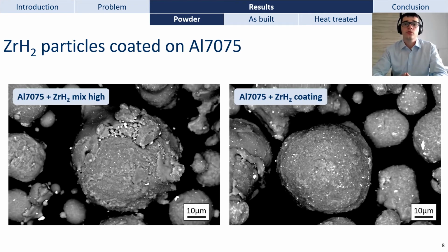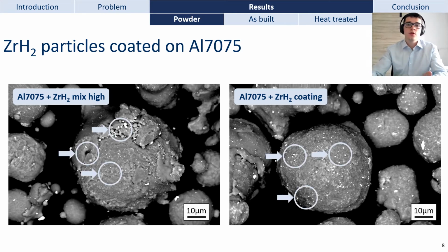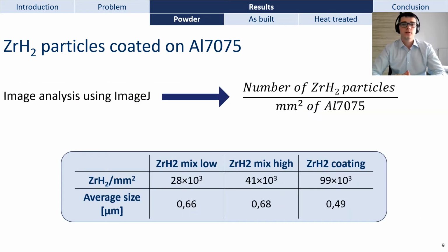Now that we have talked about the unwanted particles, let us talk about the wanted ones. That is to say, the zirconium hydride particles coated on the aluminum 7075 powder that can be seen in white on the high magnification SEM images. Once again, we will quantify the difference for the three different powders by image analysis. It is exactly the same type of image analysis as the previous one, but this time for the small zirconium hydride particles that are grafted on the aluminum 7075 powder.